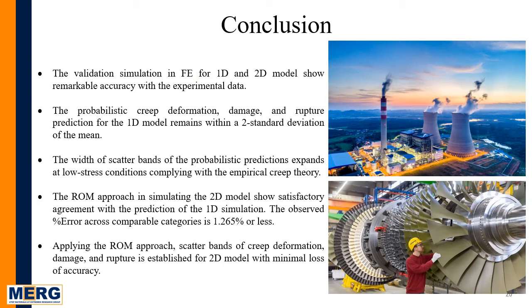The goal of this study was to introduce the reduced order modeling approach for a complex model to reduce the computational time and memory. And to that end, this study leads to the following insights. We can see that validation simulation for the finite element 1D and 2D model show remarkable accuracy with the experiment. For the probabilistic prediction of the 1D model, in most of the cases, we see the creep deformation, damage, and rupture prediction remains within 2 standard deviations of the mean.